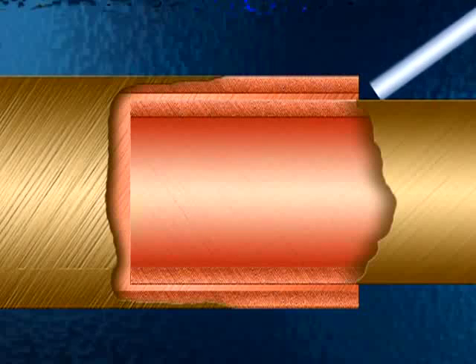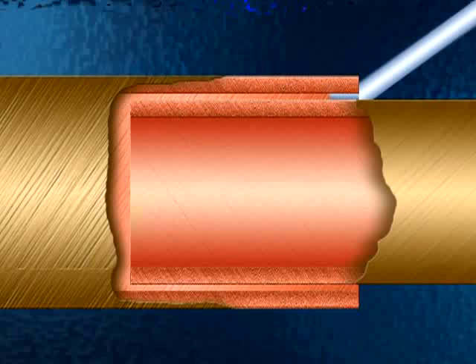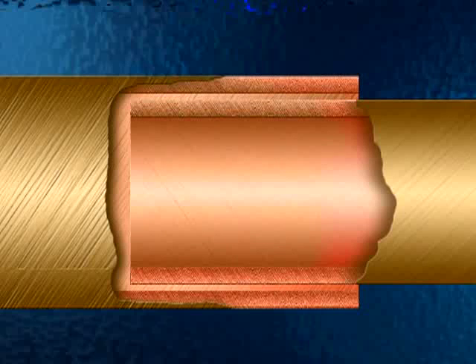Proper heating is critical to making good joints. The majority of leaks can be traced to improper heating. The reason is simple. Joint strength and soundness depend on drawing the filler metal into the capillary space. Filler metal will not flow into the joint unless both parts are at brazing temperature. Improper heating ruins capillary action, so that filler metal just piles up around the outside of the joint. Over a period of time, system vibration will cause a leak to develop.